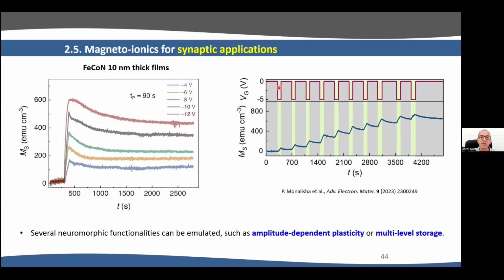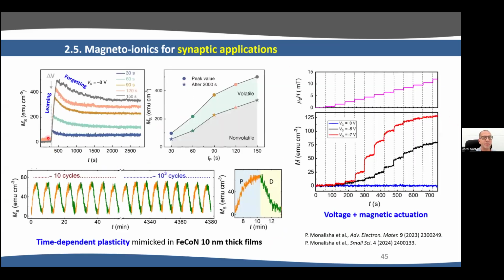Now, if we perform repeated stimulations of the material, we can get this nice multi-level, multi-state behavior, which is also needed in synaptic applications. Or you can play, for example, with the time. So here we keep the voltage -8 volt, and we change the time. So in the blue one, this one is just half a minute, and we induce something, but we retain just a little bit. As you can see, the non-volatile is just this part here. But if we increase the time that we're applying this voltage, we generate higher magnetization. We also forget something, but we retain better.